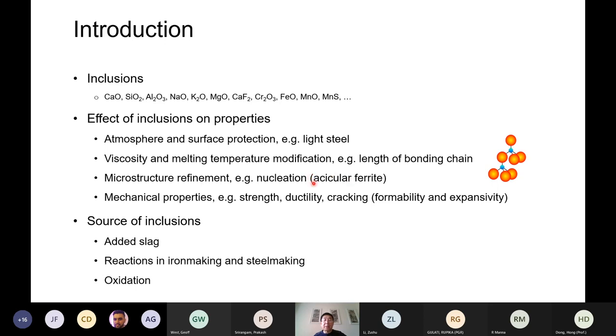There's a class of steel called acicular ferrite. Mainly, all the grades are studied from the nucleation. So this oxide can actually help the heterogeneous nucleation. But when you put those oxide particles into your steel products, the property will be changed drastically. The strength will be changed, which depends on the size of the oxide.